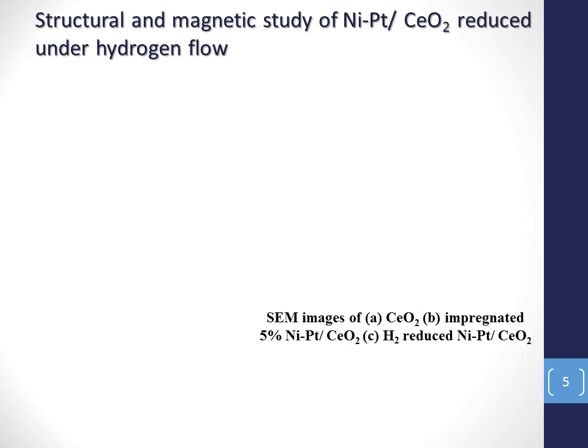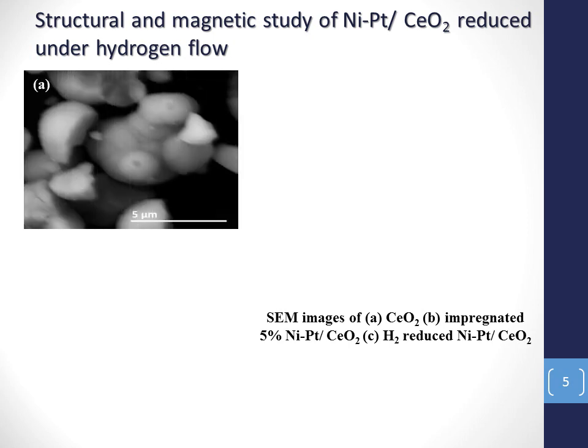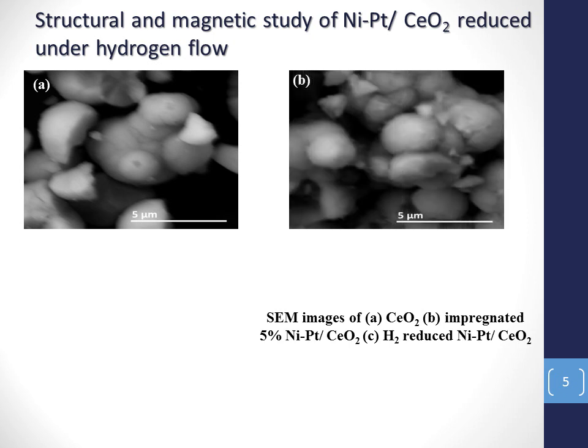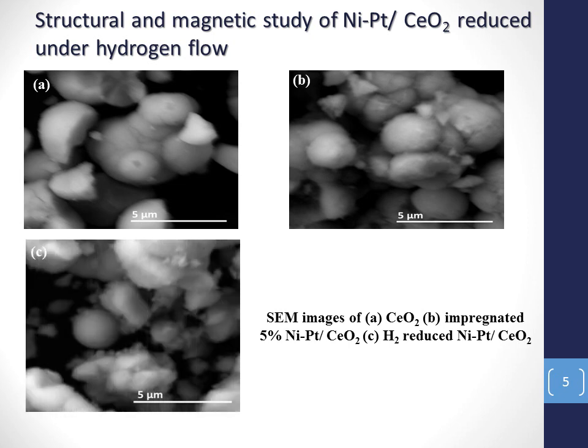The figures present some images of powders in different steps of synthesis. As seen in image A, the support shows a stack of small spherical grains with a smooth and clean surface. Their size ranges from 2 to 5 micrometers. The micrograph B of bimetallic NiPt deposited on cerium oxide during impregnation shows a morphology similar to that of the oxide. At C, the reduced one shows the appearance of a new morphology, small free clusters as well as small particles distributed on the oxide surface.